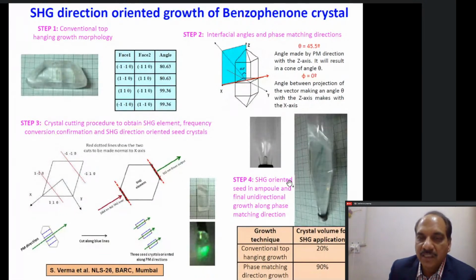And we put this seed, you can see the small seed inside this ampoule, which was then filled up with the solution. Then this crystal was grown. And now you see this crystal. It's a 9 centimeter long crystal that was grown, and the crystal volume which was usable for SHG application